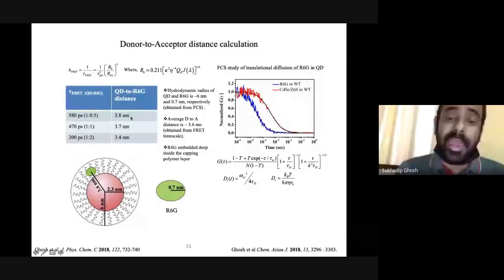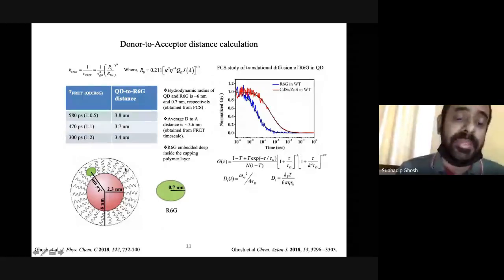And we found from DFT calculation that the size of rhodamine 6G is a radius of around 0.7 nanometer. So now if I add 0.7 and 2.3, it is not equal to 3.8. So we are assuming that this molecule is basically embedded deep inside the capping layer, so it is neither at the interface nor in the very core portion of the quantum dot.